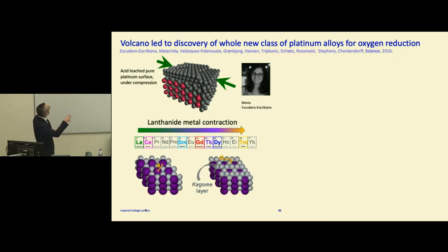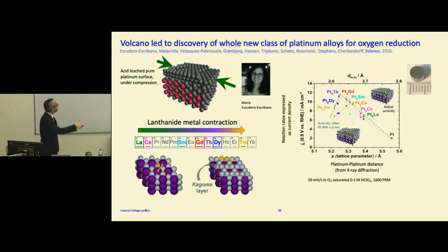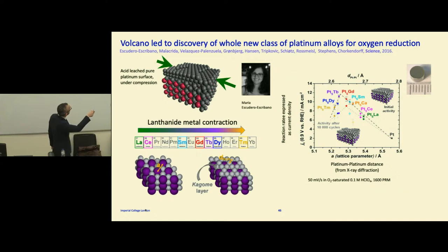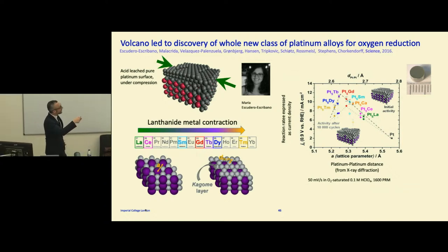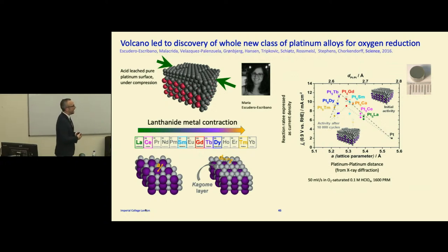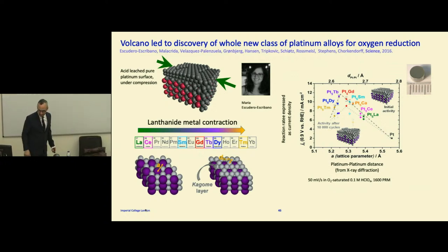And the nice thing with the lanthanides is they have quite a boring chemistry, all the same. The only thing you're changing is the size of the atom. So we think that the activity is controlled by the platinum-platinum distance at the surface. That means we should be able to reach optimal activity by just changing the lanthanides. And this is exactly what we did. We've got another volcano here, and we've got extremely high activity. A good thing about this is, if you put this in principle in a fuel cell, you could get away with using about five times less platinum. So you could scale up fuel cells more easily.